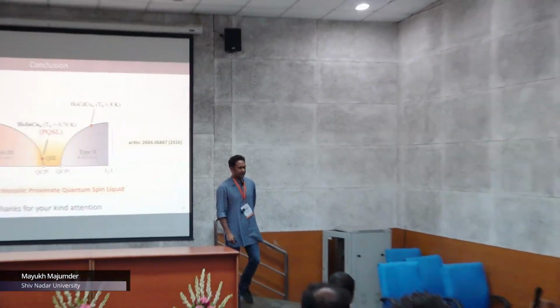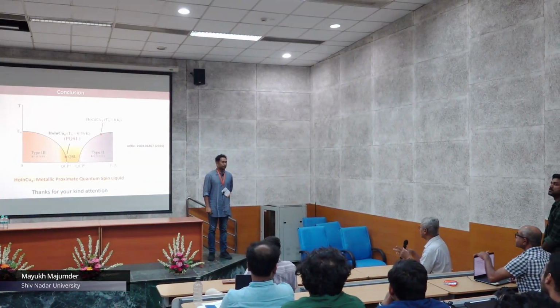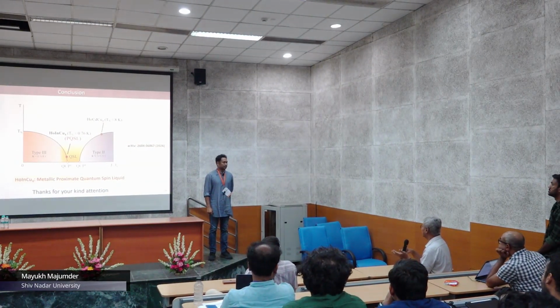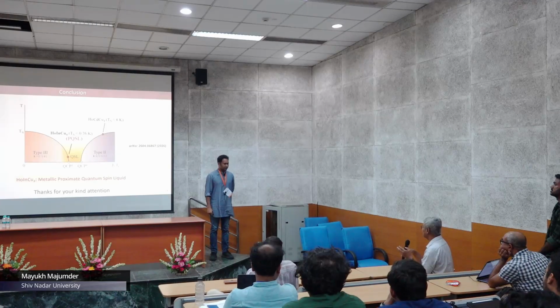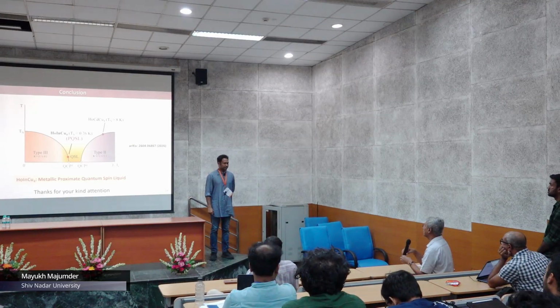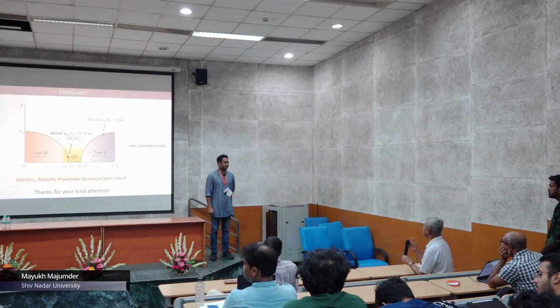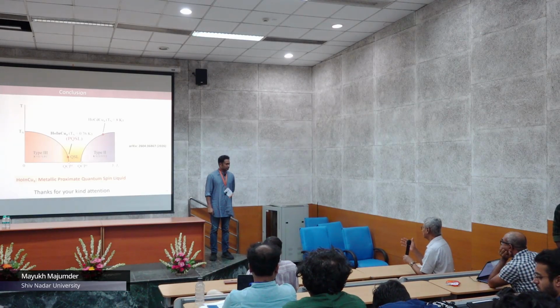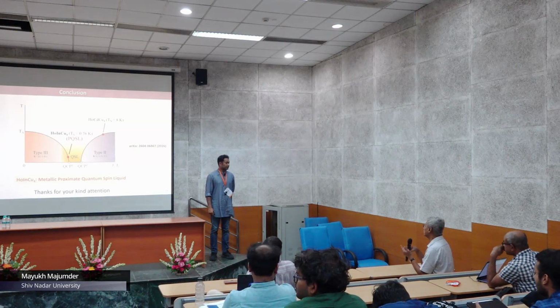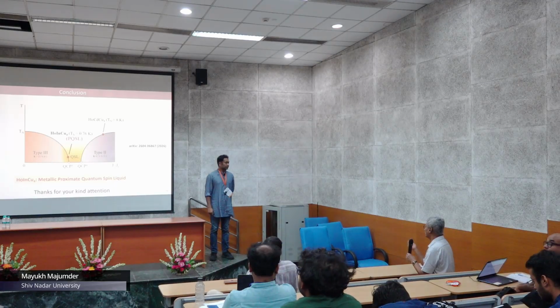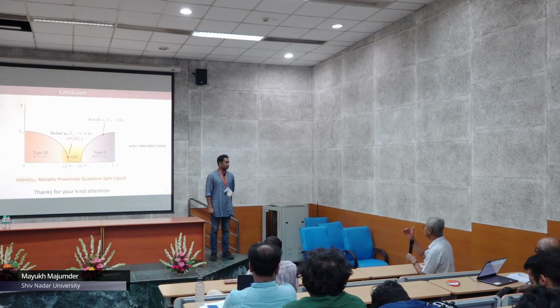Quite interesting. I'd like you to comment on the competing time scales in the problem. You have the muon lifetime itself, which is a microsecond. Then you have the spin relaxation time. One would expect that in a disordered, frustrated system, you have a distribution of relaxation times. And then you also have the Larmor precession time in a local magnetic field. Would you like to comment on how they compete and how you see the transition from the oscillatory to the relaxation behavior?